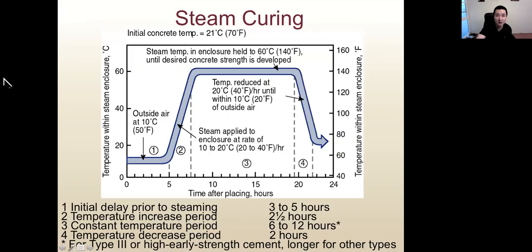So here shows a special curing method, we call that steam curing. We increase the temperature quite a lot. Here shows how we do the steam curing of concrete. The x-axis is the time after placing the concrete, and the y-axis is temperature within the steam, in degrees Celsius.